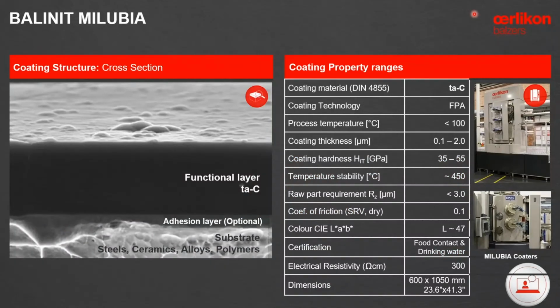A list of some of the coating properties here. You see a nice cross section again on the left, the TAC material, the coating process, the coating temperature, and thickness. Because the coating is so hard, it is limited to a thinner range of coating, 0.1 to 2 microns typically, and a coating temperature stability, which is also on the higher end of DLCs, at 450 Celsius, or approximately 842 Fahrenheit. Very low coefficient of friction and certified for food contact and drinking water contact.